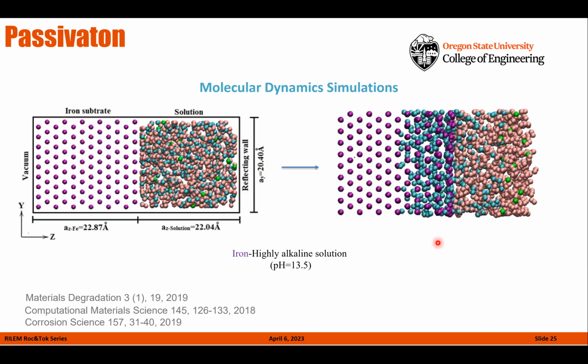And it does. You can see here that the oxygen atoms are penetrating into the crystal structure of the iron domain. And you can see that the iron domain crystal structure remains the same, but you form different forms of iron oxide and iron hydroxides.